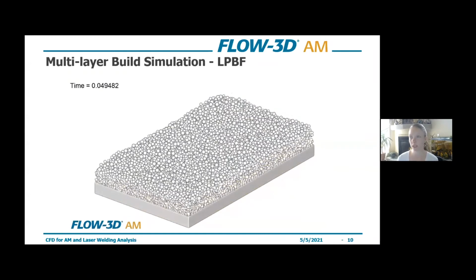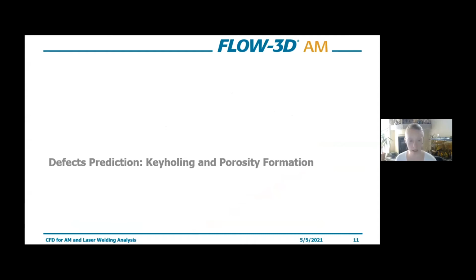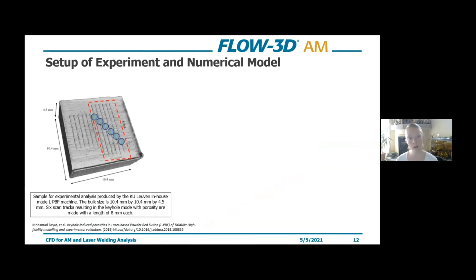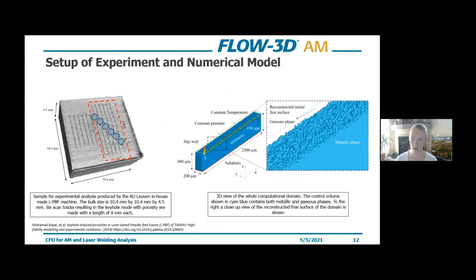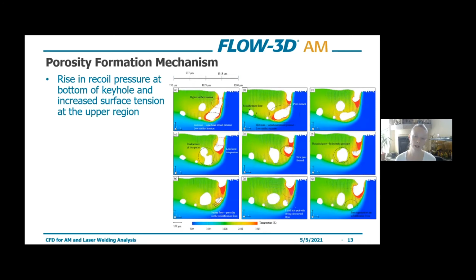So one of the key defects that I think everyone is always looking out for is porosity formation. Often this is a result of operating in a keyhole mode. Researchers at KU Leuven did a numerical and experimental study where they were qualifying the transition into keyhole welding and looking at the mechanism that leads to porosity formation from keyhole welding. They used an in-house machine, ran their experiments, and then replicated the experiments with a numerical model and compared the results. When looking at these simulations, we can get a very good understanding of what is happening at any given time during this process, and what the mechanism that leads to porosity is.